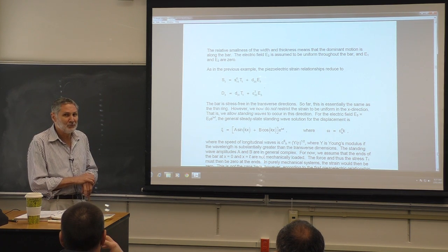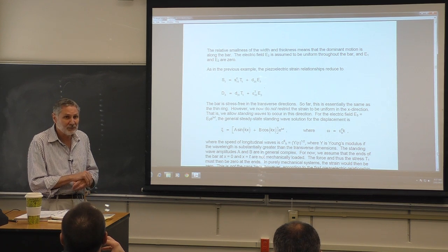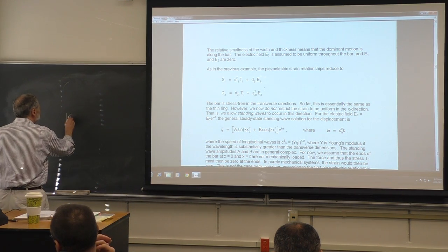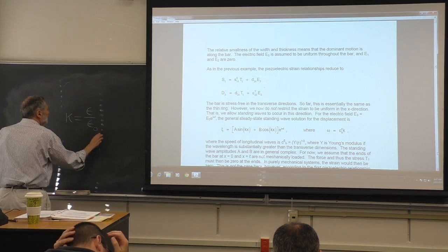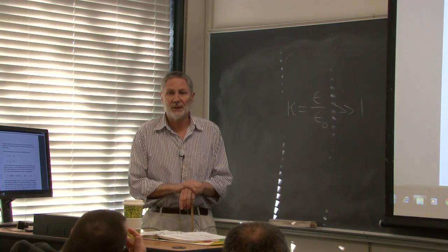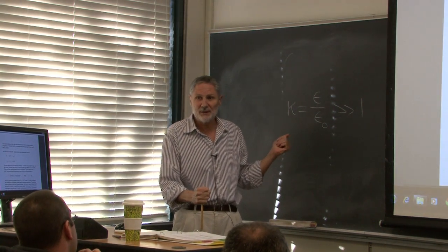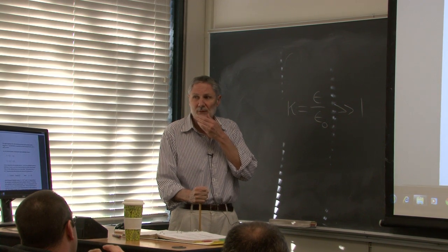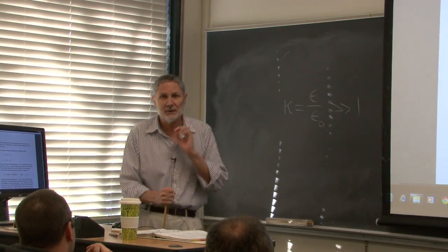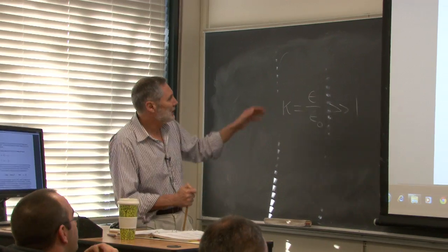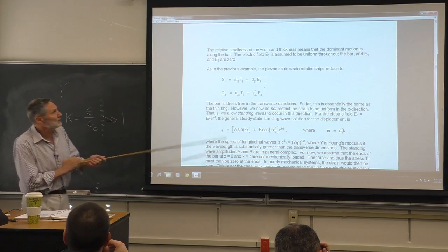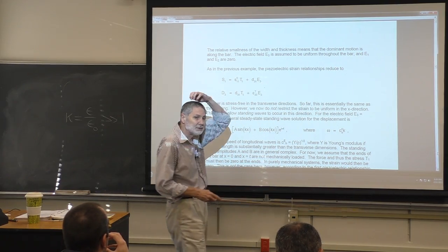And we now know that's a good approximation, right? Because the relative dielectric constant, sometimes called kappa, is typically very large here. And you should be seeing that in the experiment that you did, where you actually determined this by taking measurements. So you should be getting roughly on the order of 1,000. If you don't, then there's probably a mistake. Because of this, as I discussed yesterday, the field lines get trapped. And so the uniform field is a good approximation.